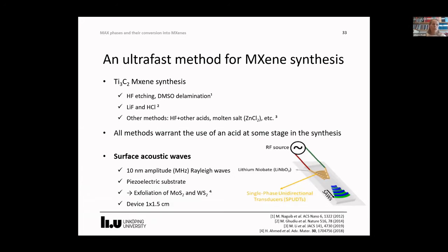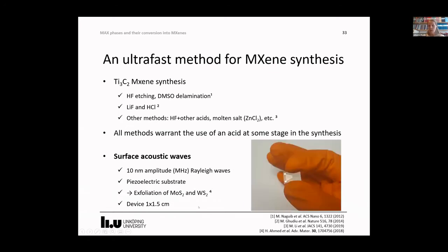And due to the very high surface acceleration and strong electromechanical coupling in the piezoelectric substrate, one can realize, for example, exfoliation of weakly bonded van der Waals compounds, such as molybdenum disulfide or tungsten disulfide. And this is what has inspired our related study on MXenes. This is what a device looks like schematically. It's maybe 1 times 1.5 centimeter. And this is what the device looks like in real life.